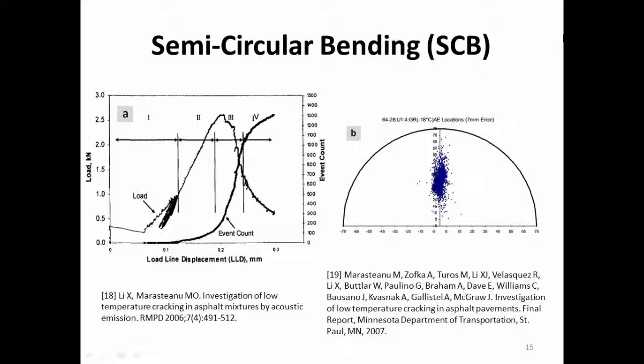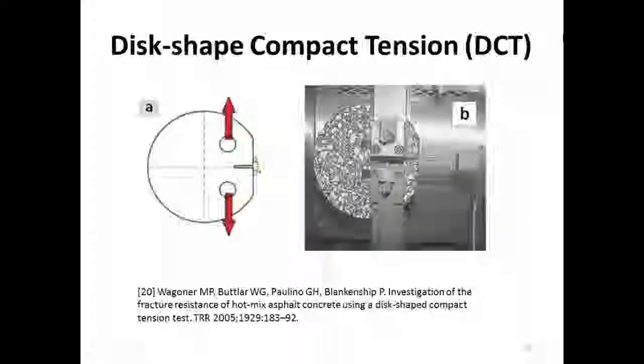Okay. So then people want to realize how the asphalt mixture cracks. So they define an area in which they count all the energy for the event count, before 95% of the peak load, and they come up with this distribution of the counts. They summarize the size of this, and this is called the fracture process zone in front of the crack tip. So basically that tells you when the crack is going to happen and when this crack is going to propagate. It's only for asphalt mixtures or quasi-brittle materials.